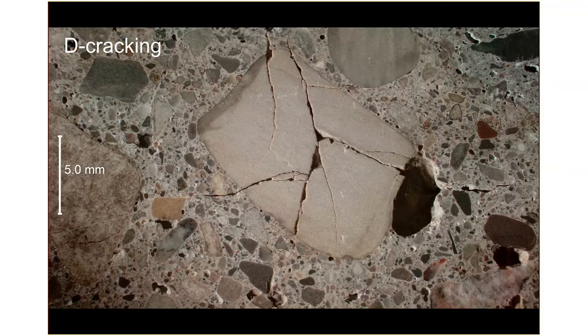And so we produce good concrete around an aggregate that is going to act like a little hydraulic ram when it fills with water and starts to break the concrete apart. Some of these particles are in the Bellefontaine concrete, and this is one of them. So you can see the aggregate is cracking all up and acting kind of like a little hydraulic ram, and starts to break apart the concrete. When all of your aggregate in concrete is made up of porous limestone, you get D-cracking, which is the kind of concentric pattern cracking at joints, especially at the intersection of joints in old pavements.